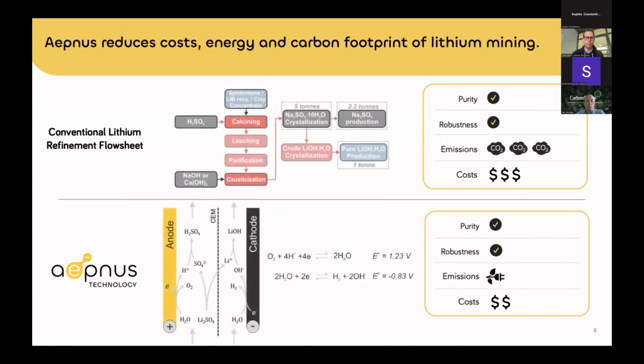Here is a little bit more granular, high resolution information of what goes on in a salt splitting electrolysis cell, such as the one that we are scaling up at the moment. Electrolysis reactors, generally speaking, contain anodes and cathodes, so negatively and positively charged electrodes that are separated by membranes. Those are fed with the lithium sulfate brine that I mentioned earlier. By applying an electric field to the system, you can make the lithium cross over the membrane. There are two reactions taking place, one on the anode and one on the cathode, both involving the splitting of water molecules to produce protons to regenerate the acid on the anode side, and the production of hydroxide ions from water, essentially base, to generate the lithium hydroxide output.